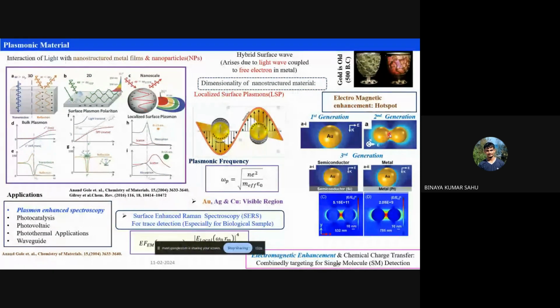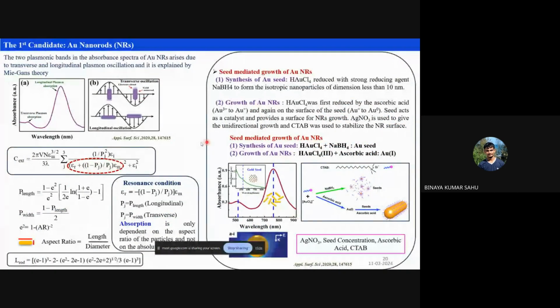But when you combine these two gold particles, you can see the confinement is increasing, because this particular junction is known as the hotspot. In this hotspot, the electromagnetic enhancement is very high, and there the signal enhancement also will be very high. And with that motivation, we started making some gold nanorods here.